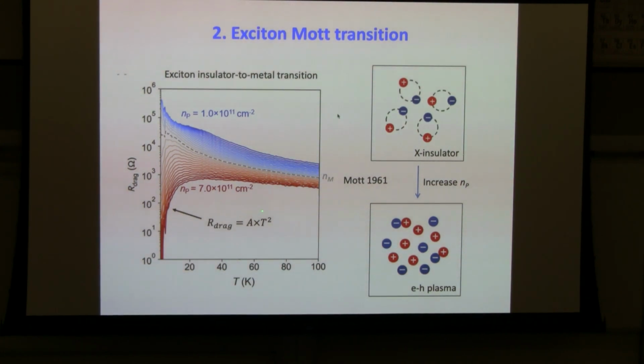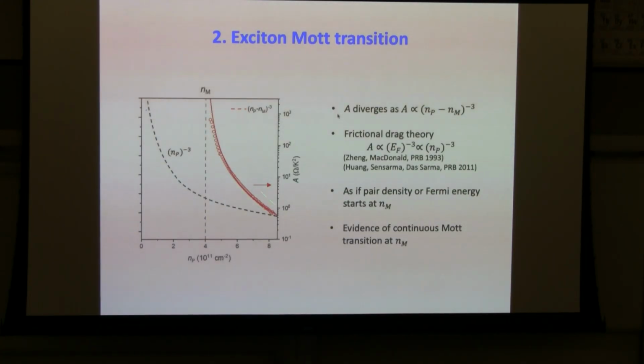So you can extract the pair density dependence of this coefficient A here, and let's look at the result. The dots are the experimental result. 4 times 10 to the 11 is the Mott density here. You can see that the coefficient diverges near the Mott density with an exponent of about 3. So that's the scaling law for the A coefficient here. And people have done theory calculations assuming that there's no exciton. So in the purely frictional drag theory, you would expect that the coefficient A would scale as 1 over the pair density to the power 3, which is this black dashed line here. It would diverge towards zero density.